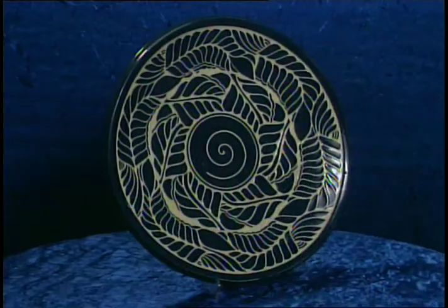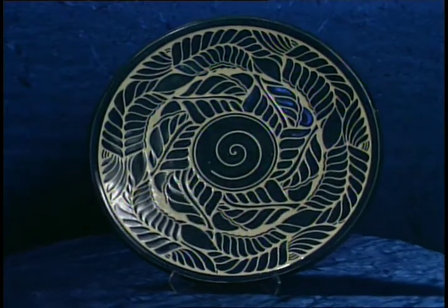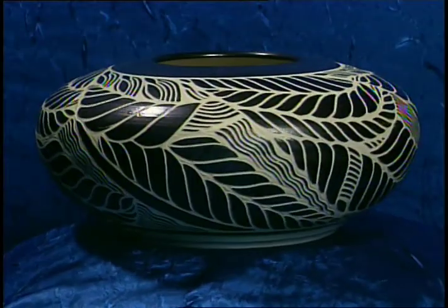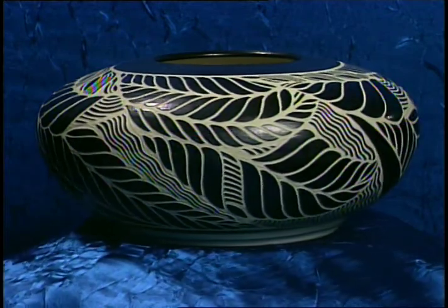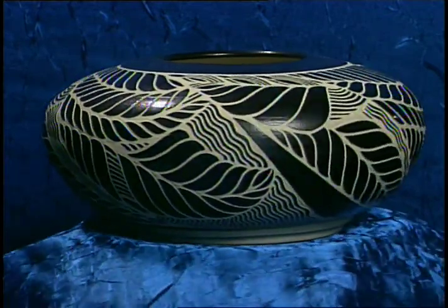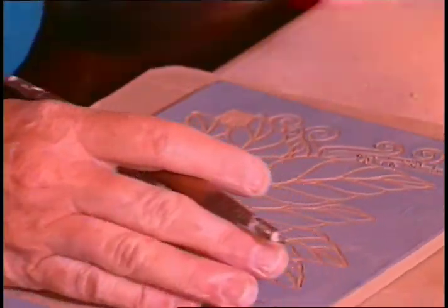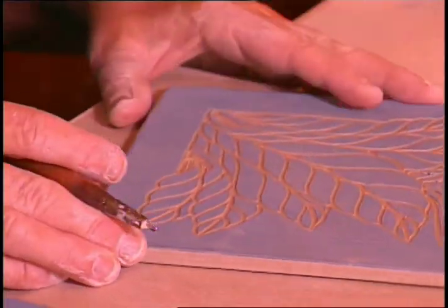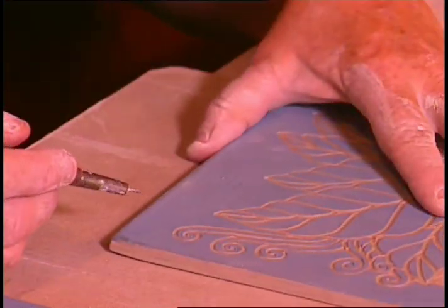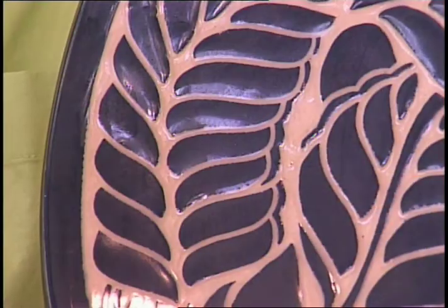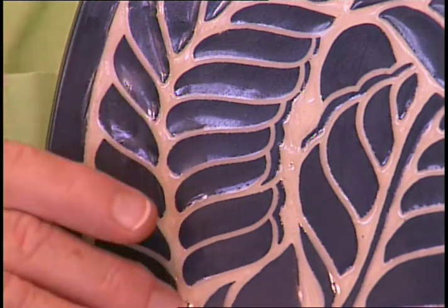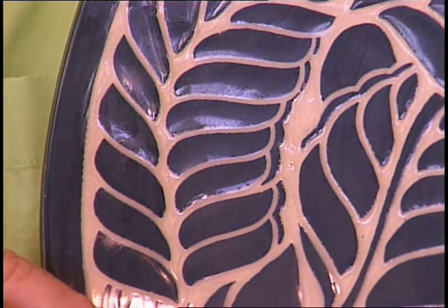The difference between the black and white and the blue and white is that the blue and white is glazed. It has a clear, glassy-like surface that is fired onto it. The black and white is fired to the same temperature, but the color is formulated to get shiny without being glazed. Initially, when I carve these pieces, the edges are very sharp and very hard. But once the piece is glazed and put into the high fire, the glaze melts and softens the edges. So it gives us this wonderful, satiny, smooth, glassy finish.